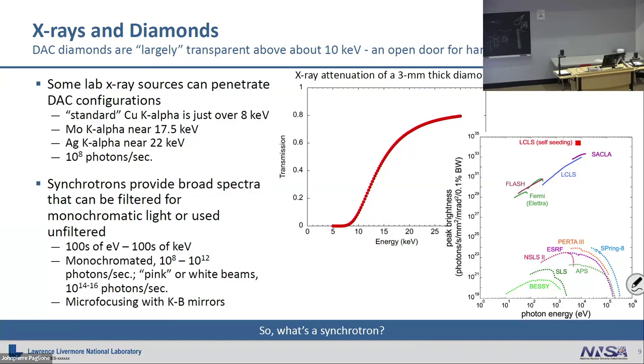The other thing that happens is sometimes they're called pink beams. A pink beam is a slightly bigger energy window. And I should say, when they say monochromated at a beam line, it depends on which beam line you're at. Some of these are monochromated down to electron volts. They will give you 10.213 kilovolts, plus or minus one electron volt. Others are monochromated plus or minus 10 to 100 electron volts or something. But 10 is pretty common. So they're actually very monochromatic in terms of percent deviation.